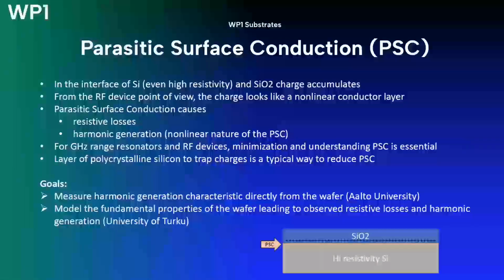Introduction to work package 1 on the substrates. What is parasitic surface conduction? In a silicon dioxide covered high resistivity silicon wafer, at the interface of the oxide and the silicon, even though the silicon is very high resistivity, a charge is accumulated. From a high frequency device point of view, that looks like a parasitic conducting layer with nonlinear characteristics on the silicon, and that creates resistive losses and, maybe more importantly, harmonic generation, like second harmonic signal. So understanding and controlling this phenomenon is of utmost importance in gigahertz range devices.